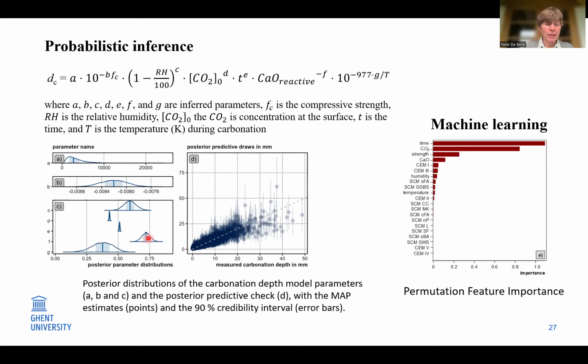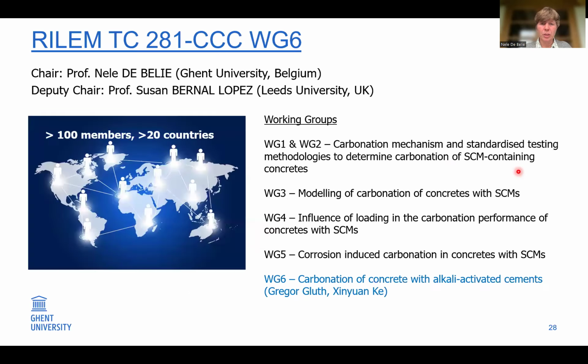The relation between accelerated and natural carbonation is seen here in the exponent D for the CO2 concentration. That is also less than 0.5, and the 0.5 would be the square root behavior. However, for the time, the T here, the exponent E is very close to 0.5, so there the square root relation is quite well followed. We have also applied machine learning, which indicates that curing time could be used as a parameter to further refine the estimation of the carbonation depth.